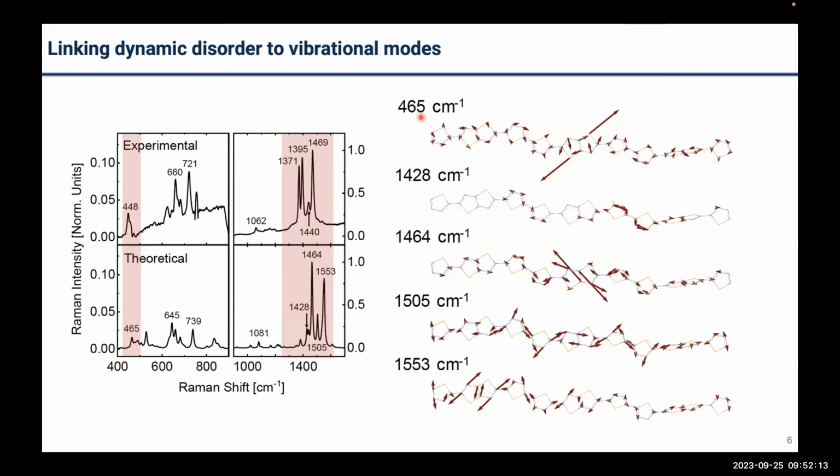Yeah, but there still will be a temperature dependence. Certainly, the zero point motion matters, but there's a thermal contribution as well, right? It can't be constant in temperature. That's right. It will be a range of temperatures where the temperature dependence is extremely weak, and at some point it starts to go exponentially. But I would say 10 Kelvin up to 150 Kelvin, you'll see no change as a function of temperature. It will be minor. Yeah, but that depends very much on the mode energy, right? And the details. Right. So I'm saying for 400 wave numbers, that will be.